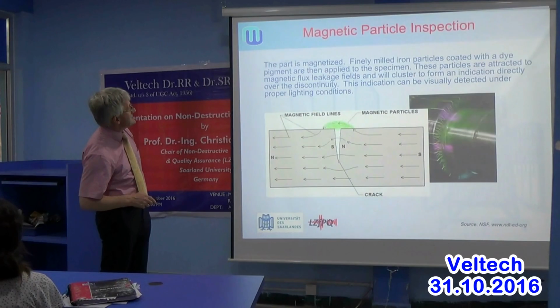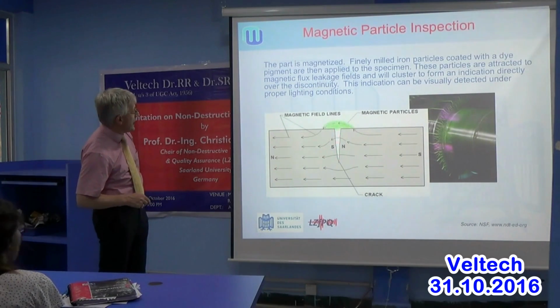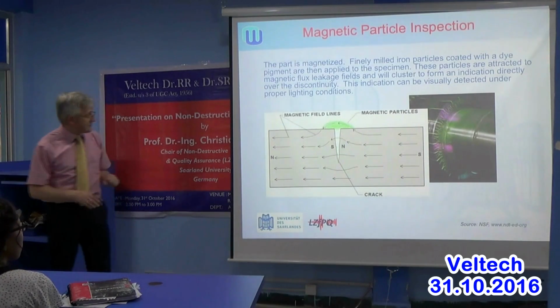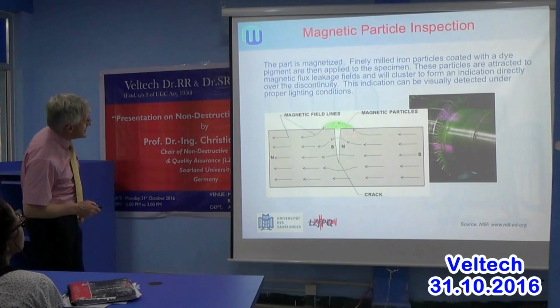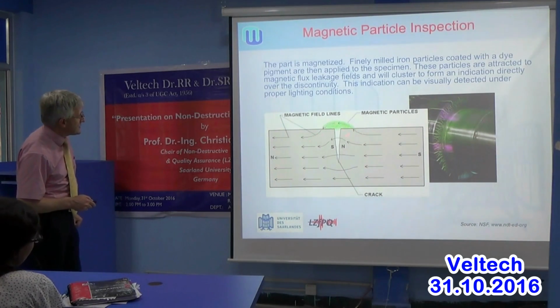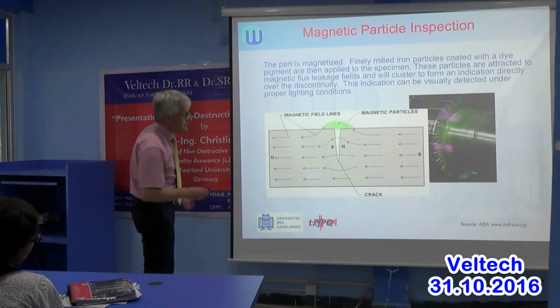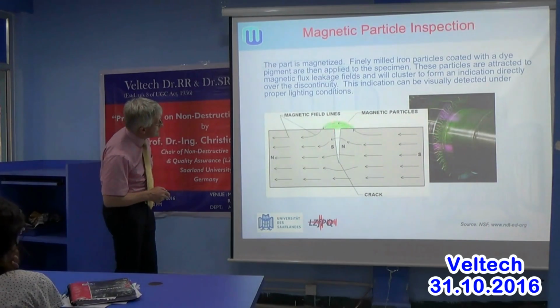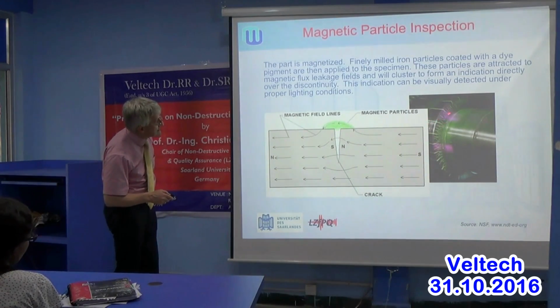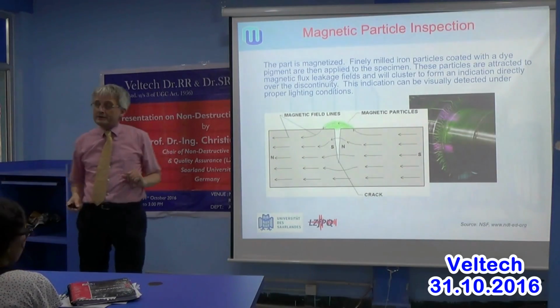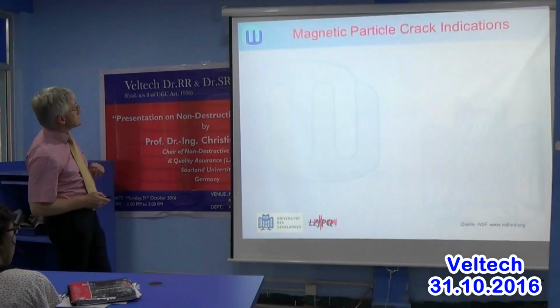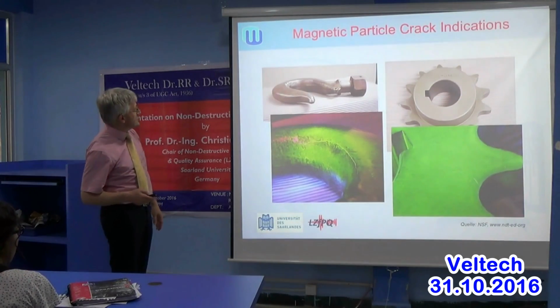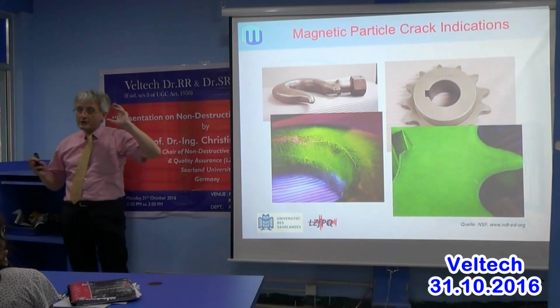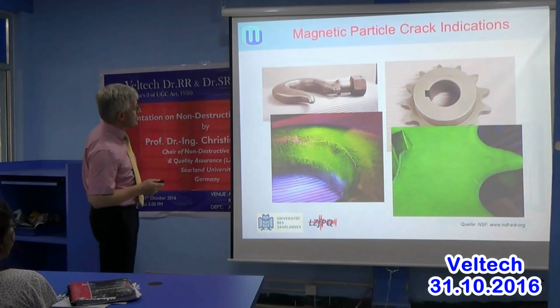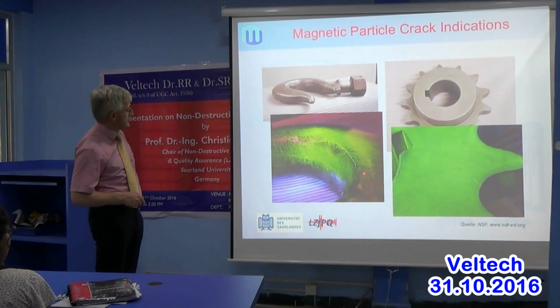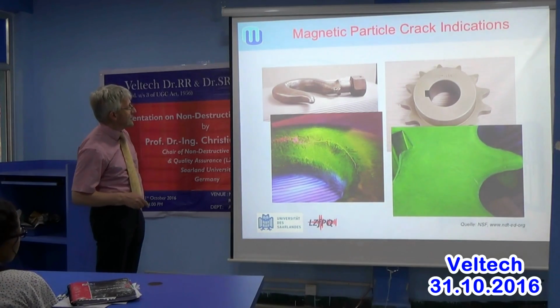Then we can use magnetic particles. Again we have a crack, and we put the component under an electromagnetic field, and if we have cracks, then there are discontinuities in the field lines. If we have a dispersion liquid with magnetic particles, they will concentrate exactly around the cracks, and we will see the crack very nicely. We can illuminate the whole thing with an ultraviolet light. These are a few very typical cases. You may have components which are overloaded, which might have got a crack or not, you're not quite sure. This is how you get those inspected, or gears here, and if you put them under the respective light, you can see quite nicely that there are cracks which you don't see otherwise.